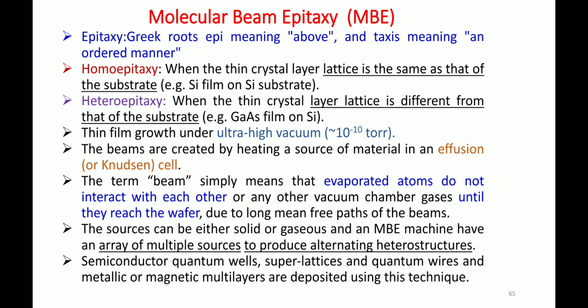The term beam simply means that the evaporated atoms do not interact with each other. This is a very important condition which you can observe in the MBE technique, that the evaporated atoms are not interacting with each other or any other vacuum chamber gases until they reach the substrate. So without any interaction or collision, they are just reaching from this Knudsen cell to the substrate. This is possible due to the long mean free path of the beams. Because there is an ultra high vacuum, these evaporated metal atoms have a very long mean free path without collision, and that's why we particularly call this flying of these atoms a beam.